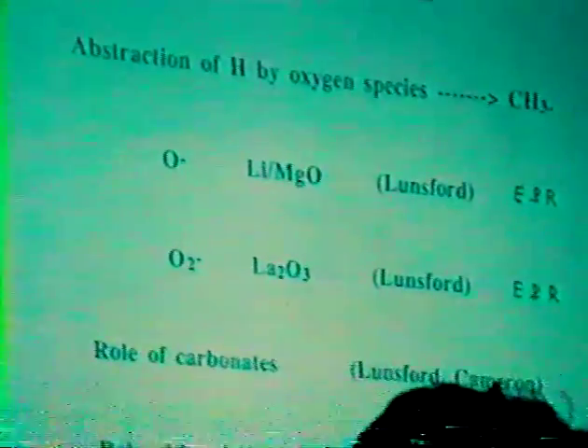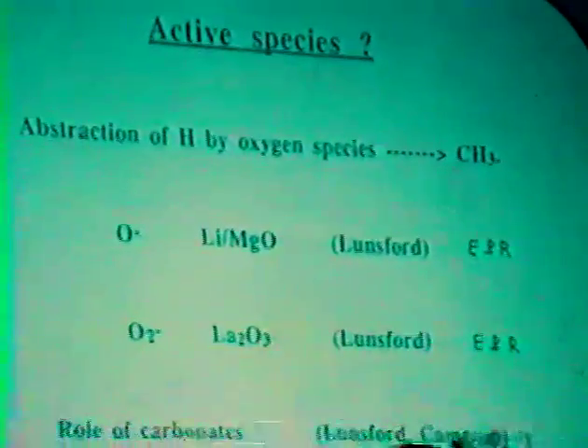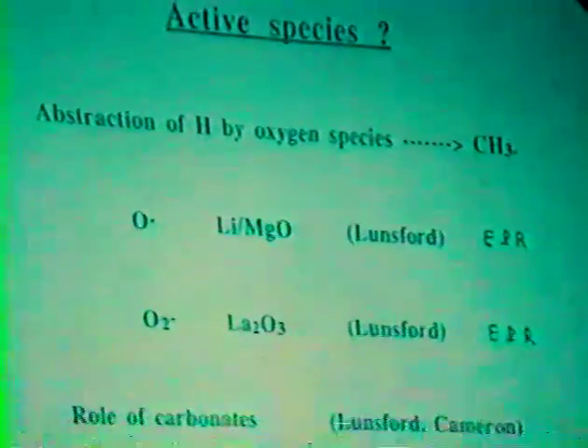The active species have been a matter of discussion. On lithium over magnesia, Jack Lunsford has demonstrated that the O- radical is the active species. But on lanthanum oxide, this radical cannot be observed. The only species observed by EPR spectroscopy is the superoxide ion. But in our lab, Catherine Louis has demonstrated that this superoxide radical is not the active species.